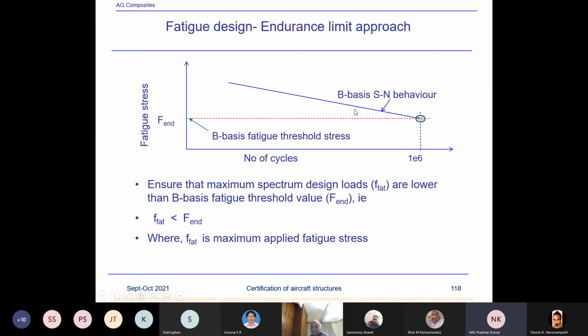So you have an SN curve, which is B basis and 95 percent based on the test data generated. And this is my allowable stress or strain. Using this allowable and the applied fatigue design load, or the stress F fatigue, I'll calculate the margin. That is, F fatigue is less than F endurance, and that's it. This is my compliance process, which is no damage growth based on the endurance limit approach. So this is a general approach.